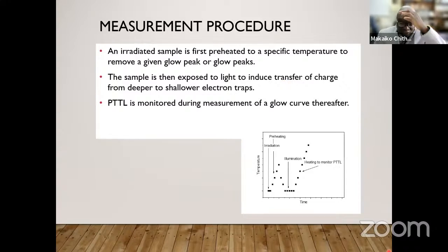So here below is a graph that explains the process. This is a temperature-time sketch. You start with irradiation. This here is the preheating process. The sample is then cooled back to room temperature. At this time, you illuminate your sample, you expose it to light, and then you heat it again to high temperature. And it is during this stage that you monitor the phototransfer.